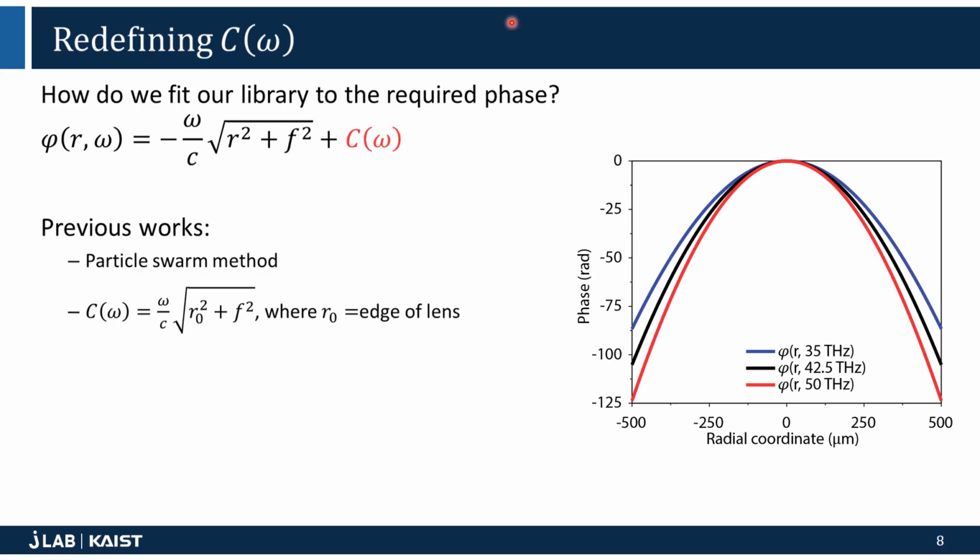To do this metalens design, we first have to see what it actually requires to make an achromatic metalens. For a lens, the phase at any given position and frequency is related to those 2 components and the desired focal length, f. This, however, means that the phase of any metalens at any position varies a lot with respect to the frequency, as you can see in the image.